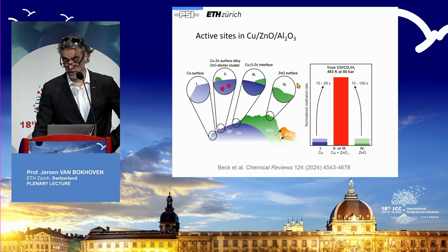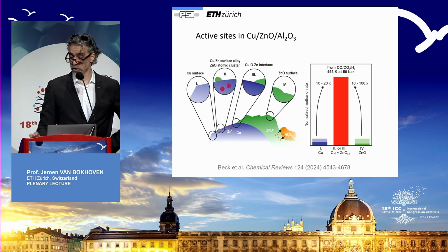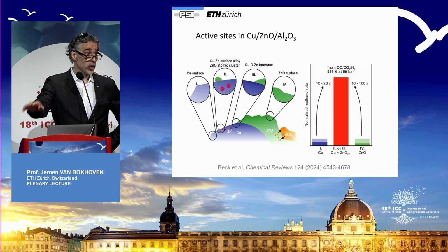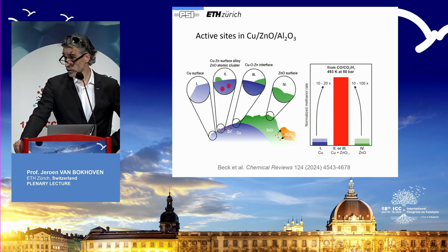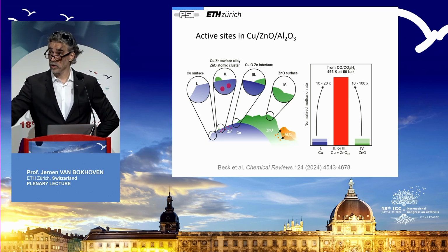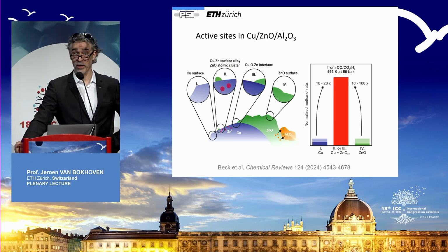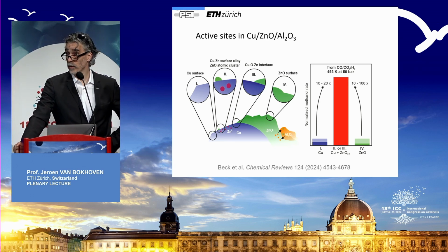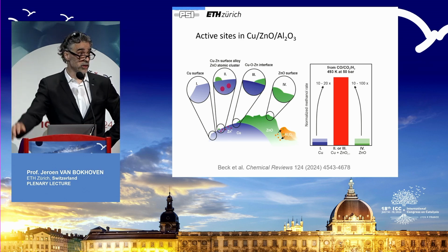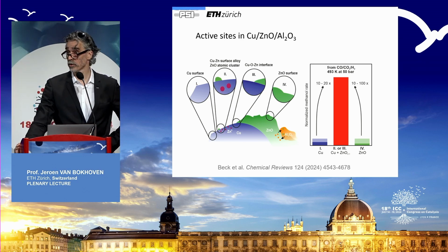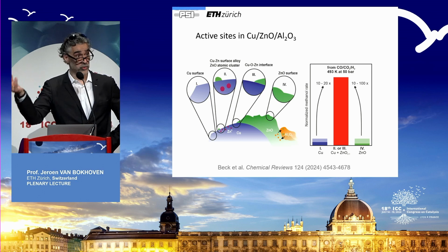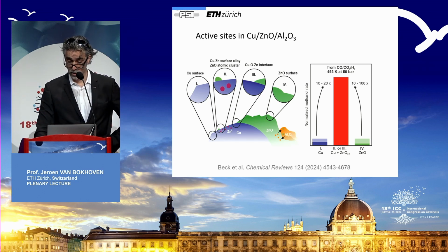provides catalytic activity. The beauty of this system is that a copper-only system is active for this reaction, as well as the zinc oxide-only system is active for this system. However, if you combine them in the right way, the activity goes way up. So here, the multi-components really lead to a synergy, to a much higher catalytic conversion. And of course, it's very interesting to try to understand why this actually is and how this functions.